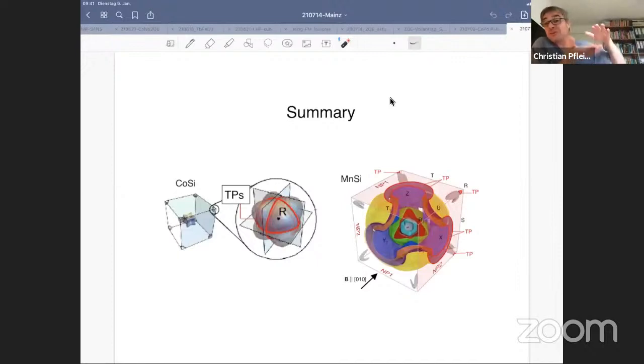But the point is the following, right? You're not going to get a gap that allows you to do a cut such that you can see the Fermi arcs connecting basically the charges in the zone center to the nodal planes, because you have the nodal planes on all three sides for the cobalt silicon. For the MnSi, you suppress the nodal planes due to the ferromagnetic magnetization, right, in one direction, and because of that, you expect Fermi arcs.